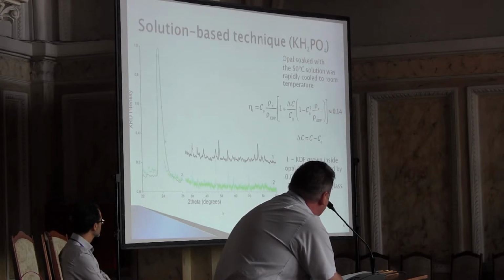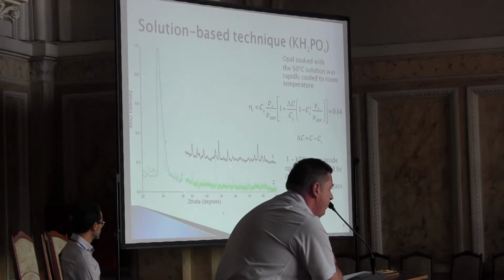In this case, the filling degree is higher, but KDP crystals grown inside opal pores are not classical KDP. As you can see from the X-ray diffraction pattern, there are more differences, and it testifies that another phase of KDP is formed under using such a method.